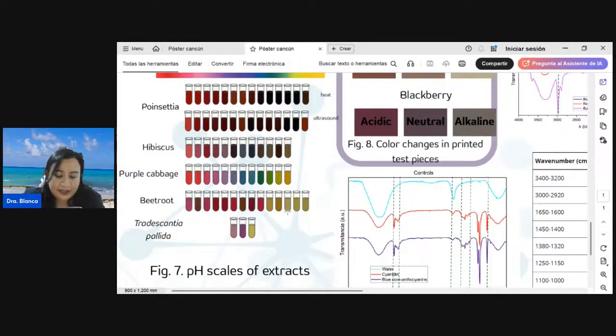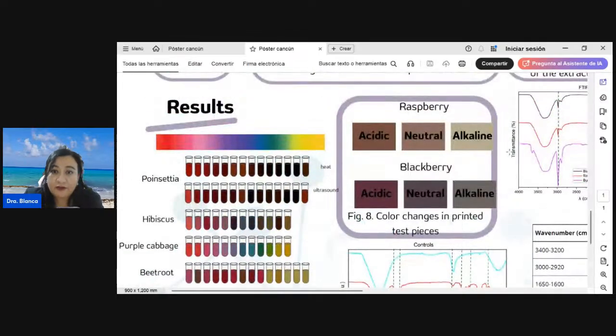Among the evaluated samples, blackberry extract showed particularly strong and evident color change. For this reason, this is the printing material changing with the pH: acidic, neutral, and alkaline. Blackberry acidic, neutral, and alkaline in the printed test pieces.